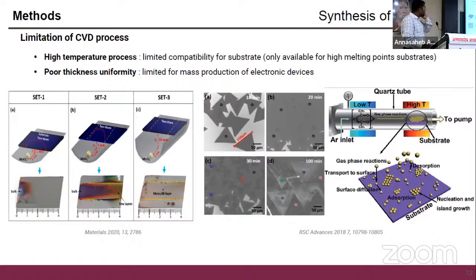As you can see in these images, here is the formation of some molybdenum sulfide using CVD technique. You can see some triangular shapes, which are basically the monolayers, and with time it can grow to cover the full substrate. But as you increase the time, the thickness will also increase, so you need to optimize that part of the reaction.